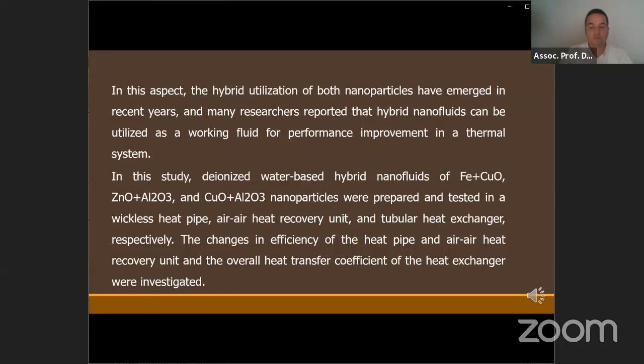In this aspect, we prepared and tested deionized water-based hybrid nanofluids of iron copper oxide, zinc oxide alumina, and copper oxide alumina nanoparticles in a wickless heat pipe, air-to-air heat recovery unit, and tubular heat exchanger respectively. The changes in efficiency of the heat pipe and air-to-air heat recovery units and the overall heat transfer coefficient of the heat exchanger were investigated.